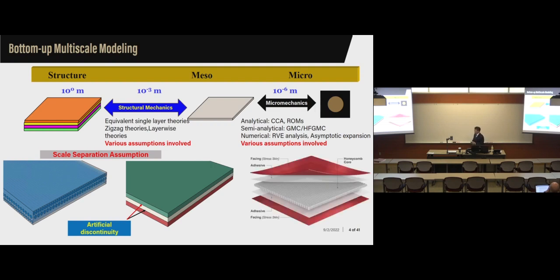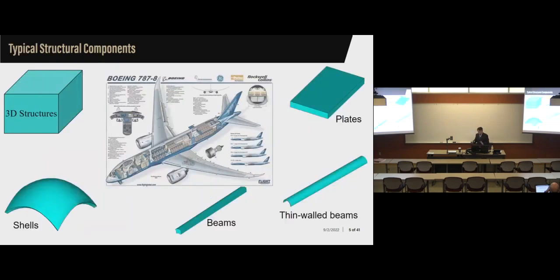And if you have a more complex system like a honeycomb sandwich structure, then you find that even for the global behavior, the displacement, the frequency, and the buckling load and all that, it does not work. Because traditionally, we take the honeycomb, do some kind of homogenization, get some effective 3D properties, then treat that as a homogeneous layer, and do a laminate analysis, or sandwich analysis. The reason being that now the size of the honeycomb is similar to your thickness. You have to do it together. This scale separation assumption does not work anymore. So that is the issue with the traditional bottom-up multi-scale modeling.